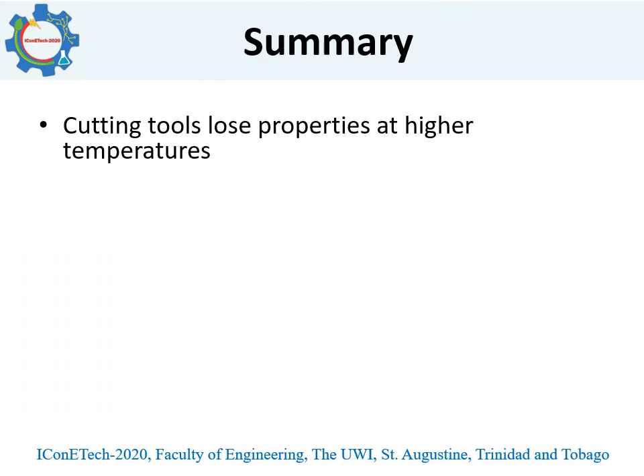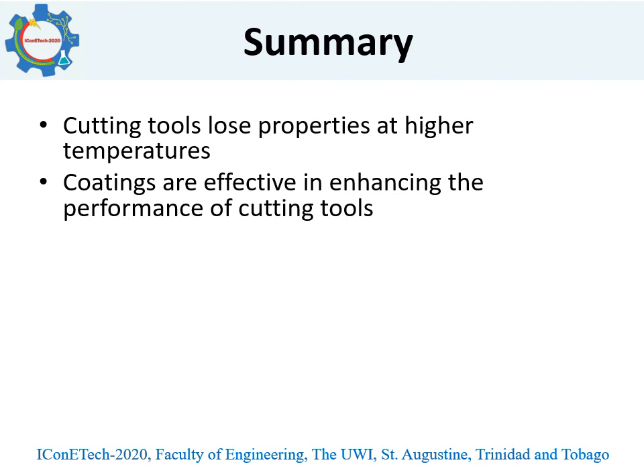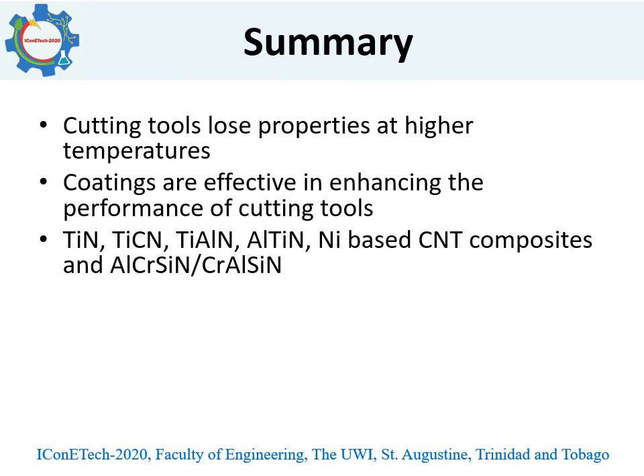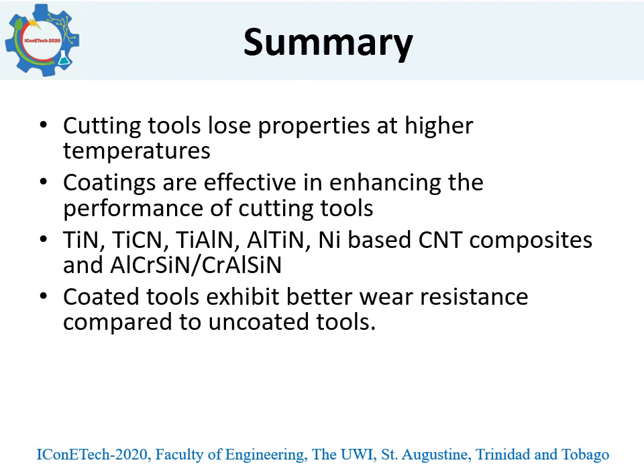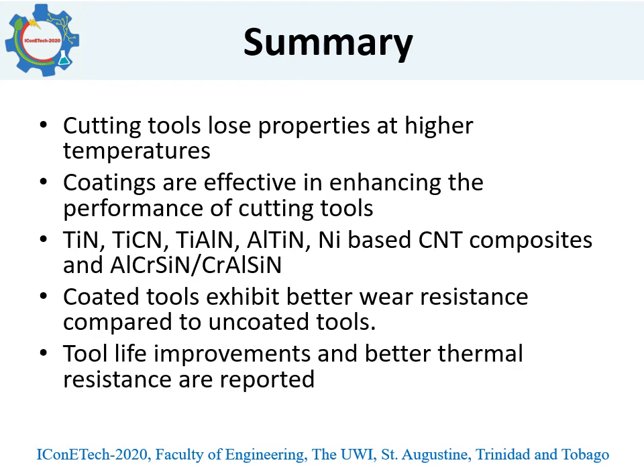So cutting tools, as we said, lose their properties at higher temperatures. Coatings are effective in enhancing the performance of the cutting tools. That means they have lower tool wear rate, better dimensional accuracy, and higher tool life. Instead of single layer, multi-layer coatings are quite extensively used, because multi-layer coatings allow for the use of carbides over a much larger range compared to single layer ones, and therefore normally these are preferred, so that they will reduce the inventory of the organizations.